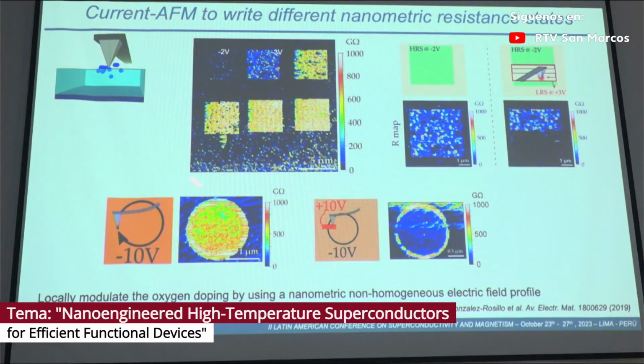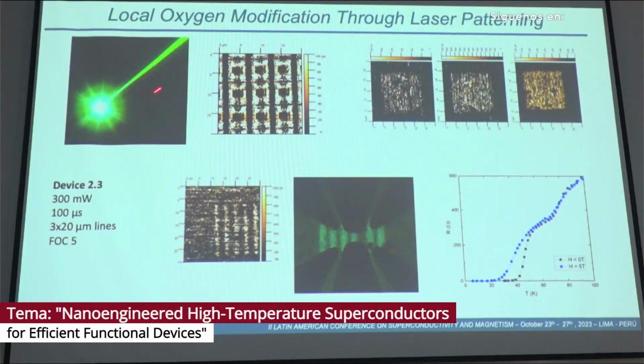And finally, to show that this effect can be introduced at nanoscale, instead of using a large contact, we use a small contact, like here, for example, a current AFM tip. By applying current with this tip, which is nanometric, we can introduce different resistance states. This would be the resistance of the system. This would be the low resistance state, and the bright ones, the high resistance state. And this, from low to high resistance state, can be reversibly introduced at nanoscale by using these current pulses with the AFM. Also, it can be generated using heat instead of current.